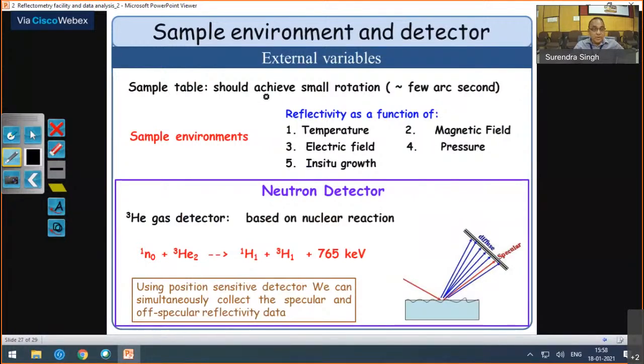But the sample table should achieve a rotation, if you are doing it in the theta variation mode, within a few arc seconds. Okay, because in that step we do the reflectivity measurement. And your sample should have all the environment.